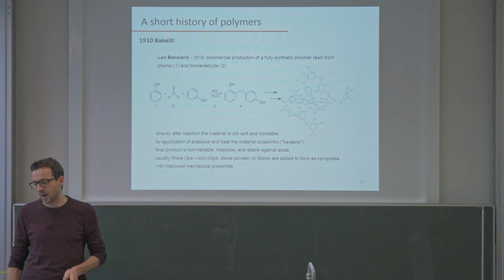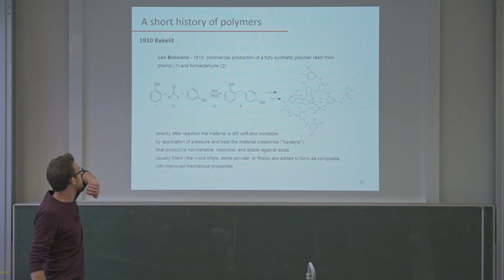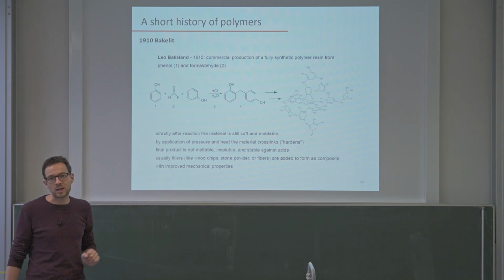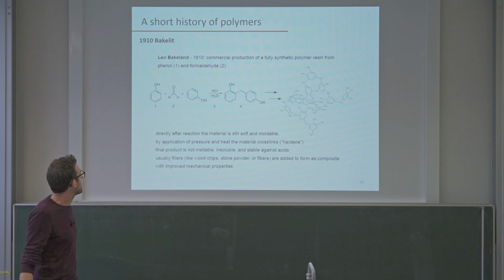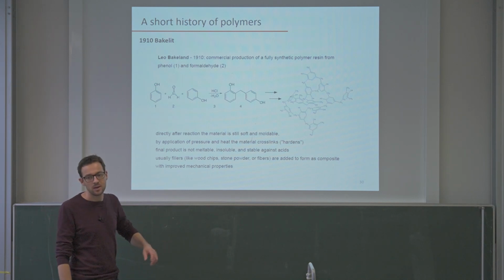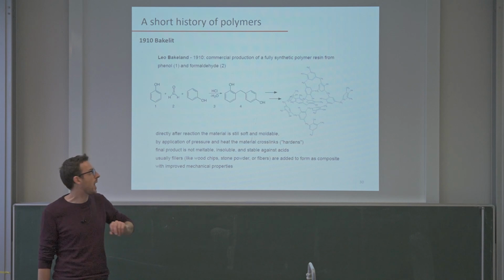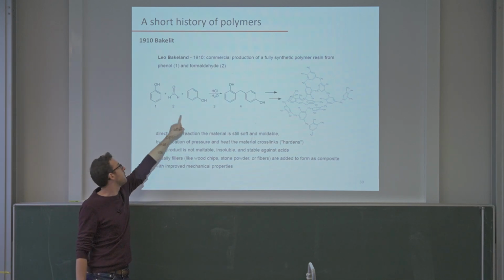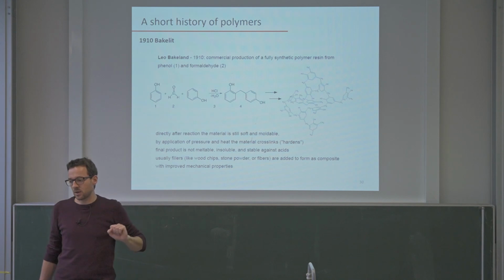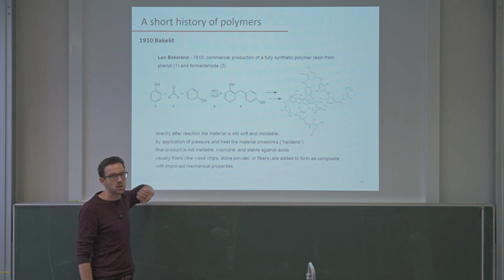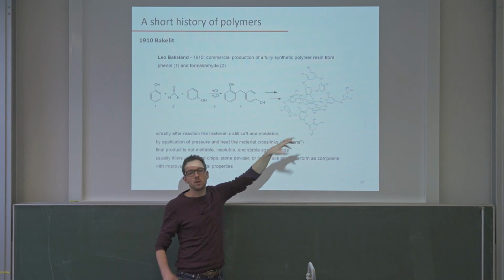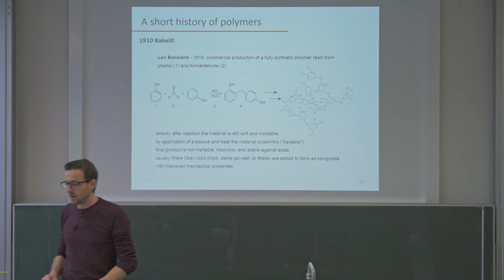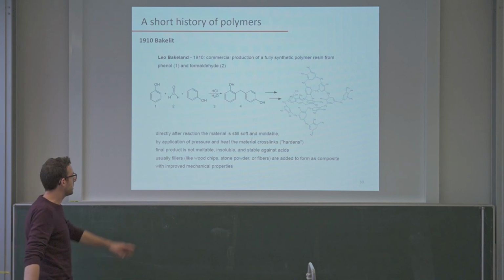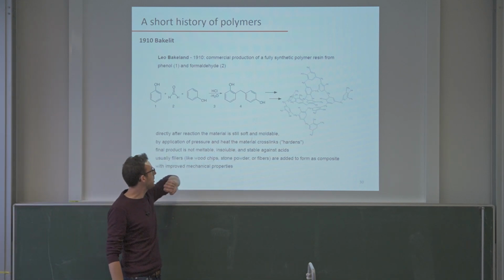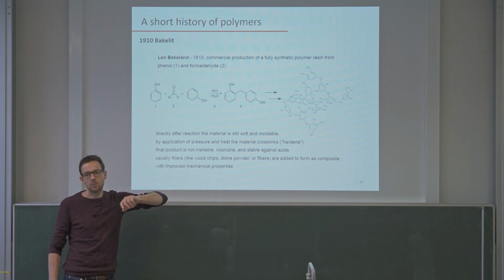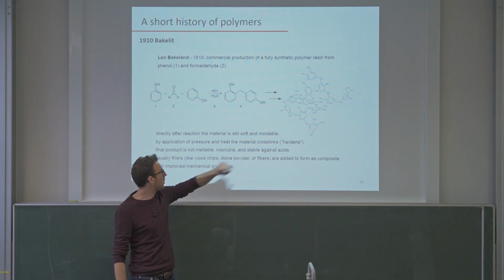until Leo Baekeland discovered a polymer that is known as bakelite. And what he did is he took two substances that are, let's say, semi-good for your health, phenol and formaldehyde. And he discovered that if you add a little bit of acid, then these things will start to polymerize and form very extensive networks. And he saw that this material in the beginning was still soft and moldable, and eventually if you heat it up, it more and more starts to cross-link, so hardens.